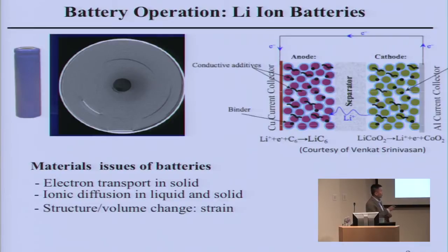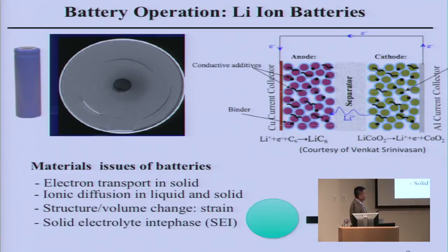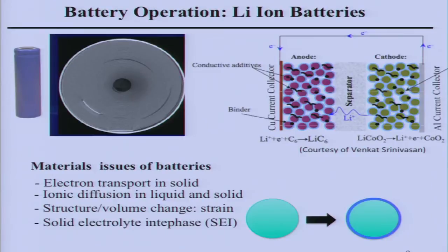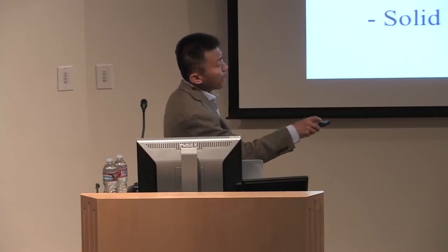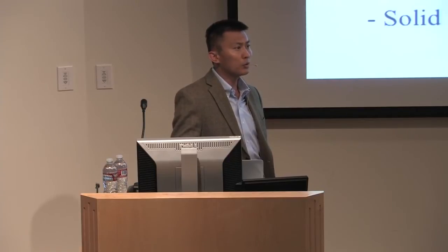And then you want this structure to be stable, with the volume change small. In order to accommodate lithium and electrons coming in and out, they all have volume, particularly the ions. So you need to make sure that this change is small. Eventually, the interface, the surface of each of these particles, needs to be stable. They're soaked in electrolyte for 3 years, 5 years, 10 years. Imagine you put something into water or any liquid for about 10 years, what will happen? Corrosion, basically, will happen. And the side chemical reactions taking place need to be self-passivated, so you have a long calendar life and long cycle life. In order to make batteries work, it's not easy.